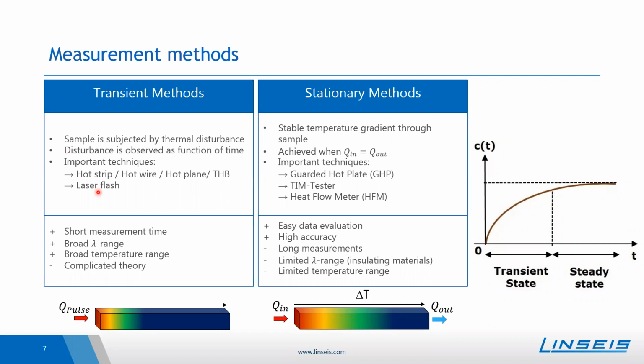Advantages is that, as already mentioned, the measurement time is very low. Additionally, one can measure a very, very broad range of thermal conductivity, so from insulation materials to very highly conductive materials. It is also possible to cover a very broad temperature range.